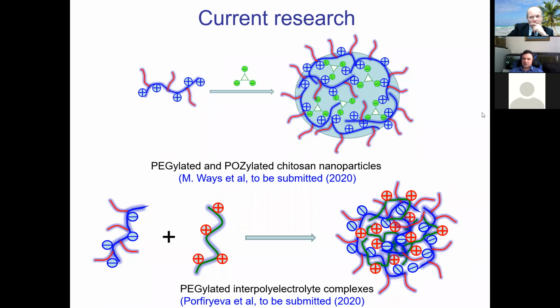In one system, we looked at chitosan that was modified with various polymers. This was also done in collaboration with Professor Hoogenboom, and we designed nanoparticles with tripolyphosphate. And in another study in collaboration with Dr. Ruslan Mustafin, we've developed a system based on interpolyelectrolyte complexes, when we PEGylated one of the polymers and designed PEGylated particles. We also demonstrated that these particles show different levels of efficiency even in vivo.